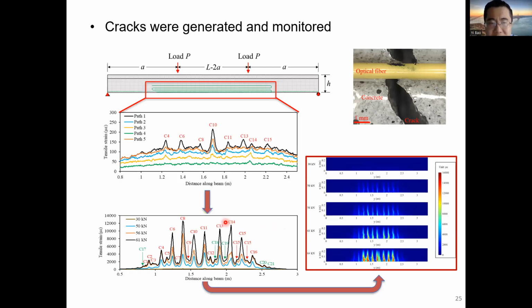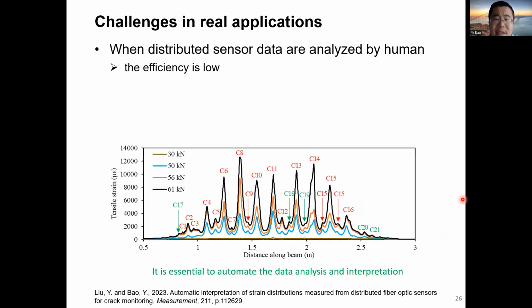And after we generate the strain distribution, because we deploy the sensors at different locations, we can replot the strain distribution, and we can use a linear interpolation method to estimate the strains between the different lines. In this way, we were able to generate two-dimensional plots to visualize the initiation and the development of cracks in the concrete beam. This gave engineers a method to easily visualize the damage conditions in structures.